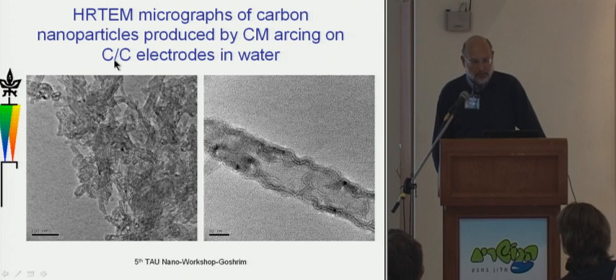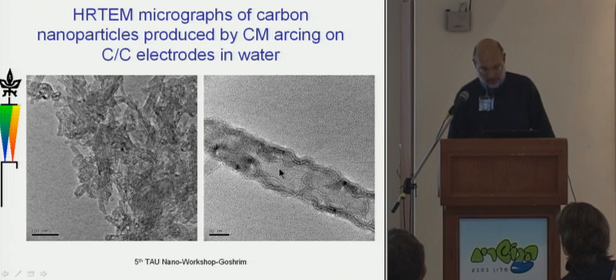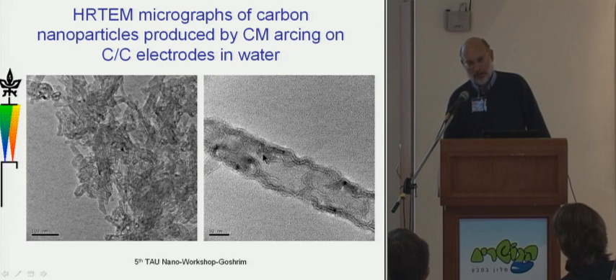If you use graphite particles, so that the only material that we're putting into the system is carbon and H2O, in other words, hydrogen and oxygen, then we can get various kinds of what looks to be very poor nanotubes being formed in the liquid.